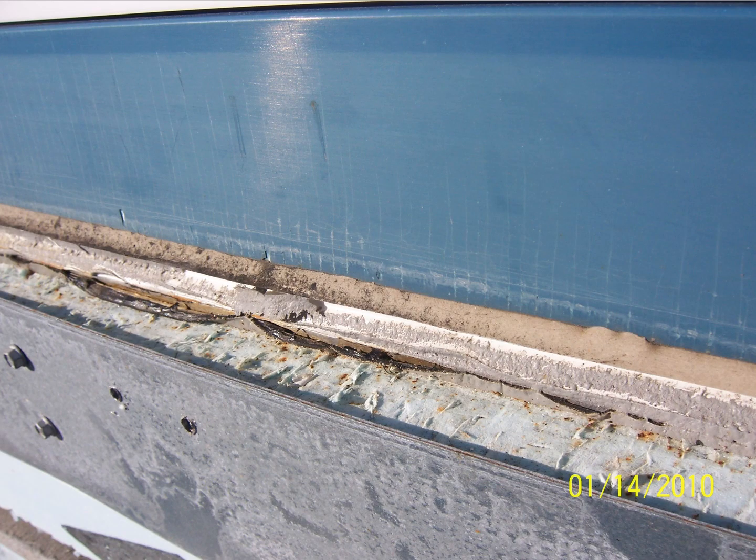We didn't believe this, and this picture confirms our conviction not to use this type of plating. This is a picture of flat stock that was stamped from G90 galvanized steel. The flat stock was 4 years old. The facade had to be removed due to numerous leaks into the building. But notice the rust that is showing up on the top edge of the steel. The galvanizing did not migrate to protect the edge of the steel.